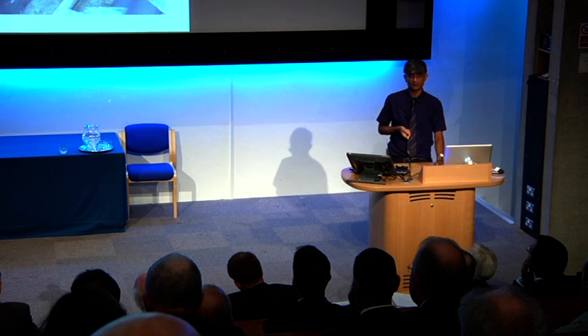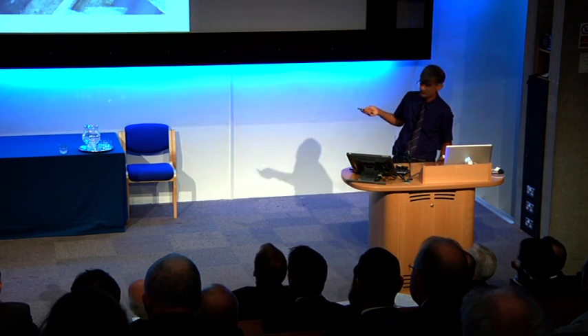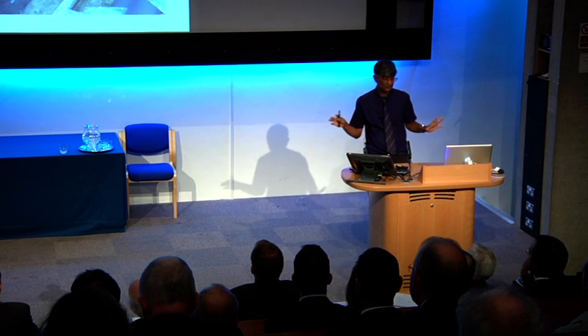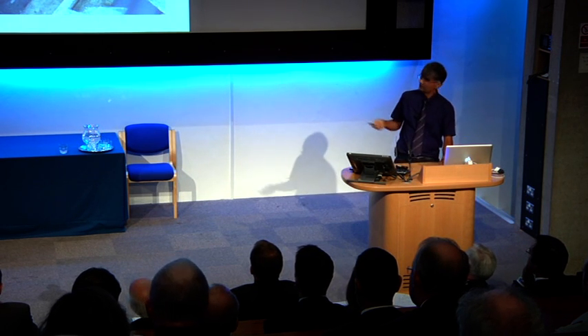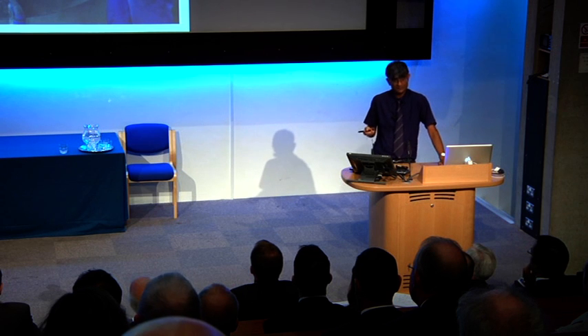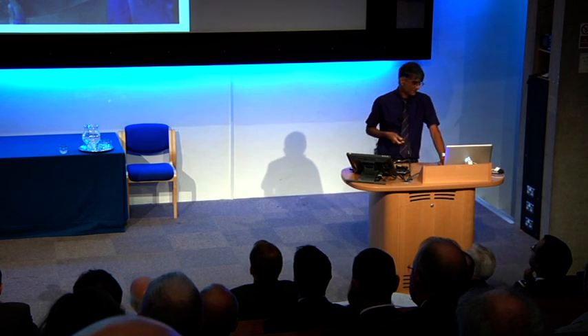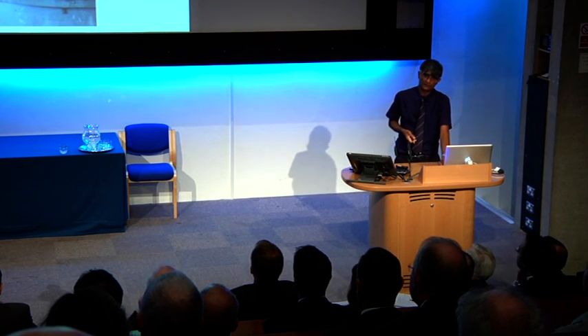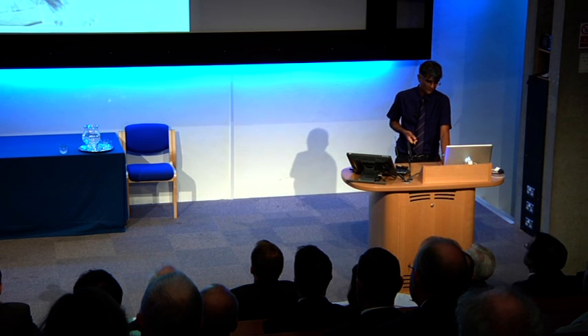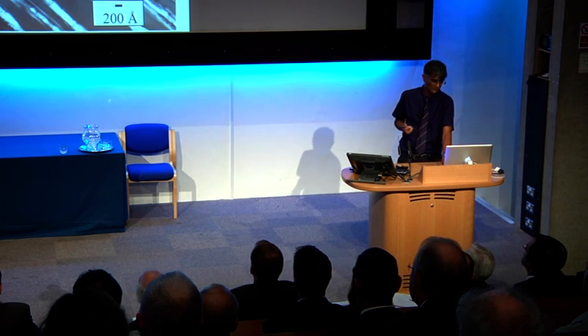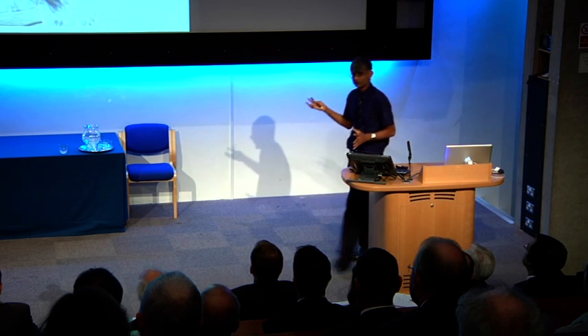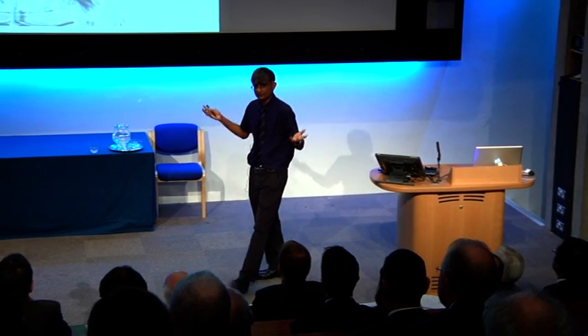This is a project we were working with Rolls-Royce to make shafts for our engines. So these are very big, and we can produce the structure uniformly. It is austenitized as usual, okay? You then take it out of the high temperature furnace and you put it into a salt bath, which will be at 200 degrees centigrade, and you hold it there for long enough to produce the structure.